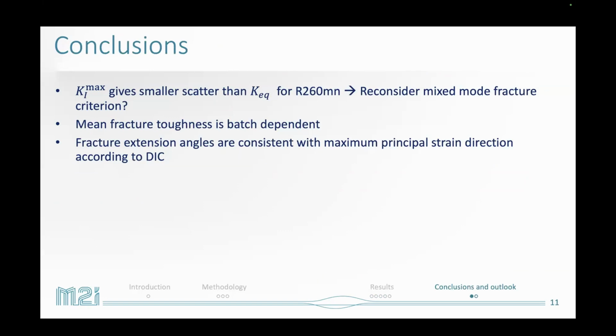This brings me to the final conclusions. So K1 max gives a smaller scatter than K equivalent in evaluating the final fracture for R260MN. The fracture toughness, the mean fracture toughness, is batch dependent. And the crack growth paths are consistent with the maximum principal strain direction.